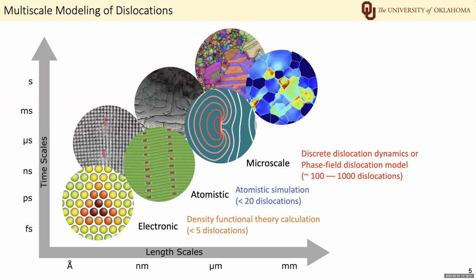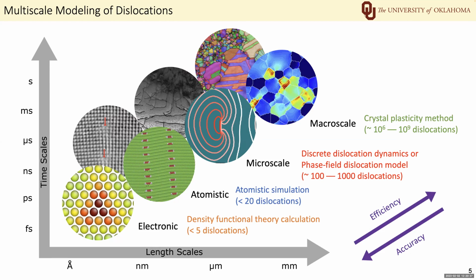At the micro scale, we can use either the discrete dislocation dynamics or the phase field dislocation model. The simulation cell can contain up to 1,000 dislocations. At the macro scale, we can use the crystal plasticity method. The simulation cell can contain up to 1 billion dislocations. So as we move up the scale ladder, the computational model would have a higher efficiency, but a lower accuracy.